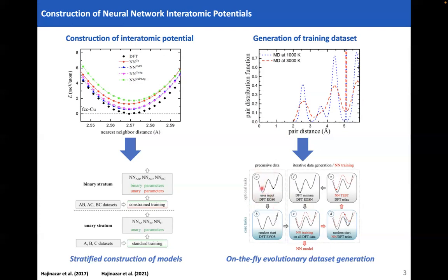Once you were done with this search, these data are being collected and used to fit a machine learning model. And then next, and in all subsequent cycles, what you do is the same search, but instead of DFT, using the machine learning model which is produced in the previous cycle. Then you do the search again at a range of pressures from 0 up to 50. Of course, you can change it.